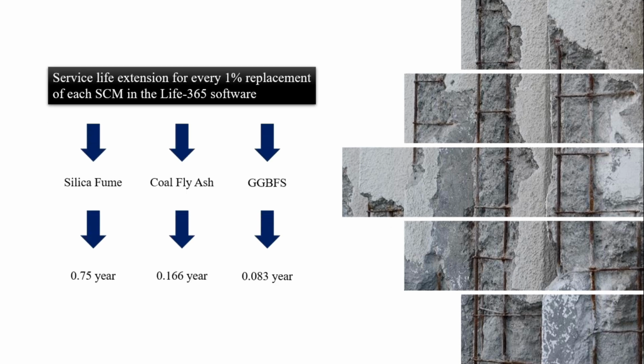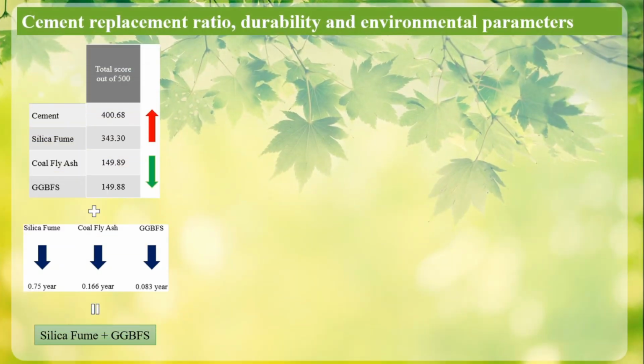To evaluate the effect of SCMs on concrete durability, a 1% replacement of each material was analyzed using the Life-365 software. The results showed that silica fume, followed by fly ash and then slag, provides the greatest increase in service life. Considering the high durability performance of silica fume and the low environmental impacts of slag, as well as the availability of both within the country, these two materials were selected to replace 40% of cement.